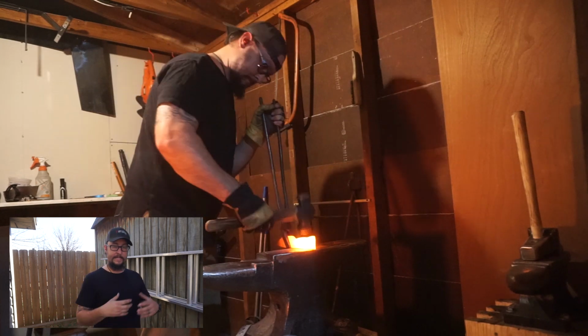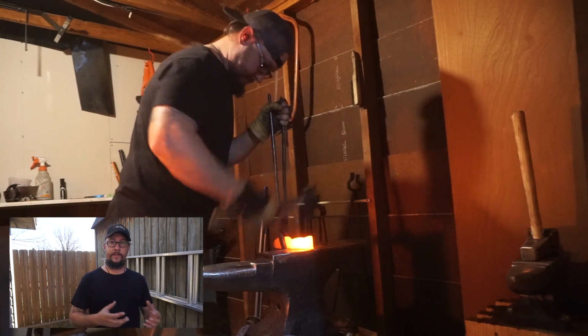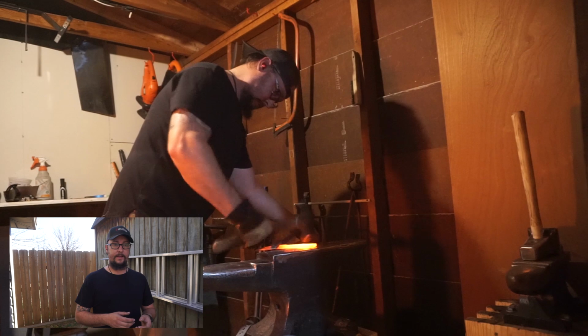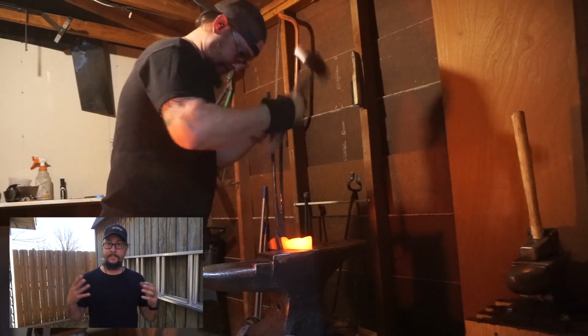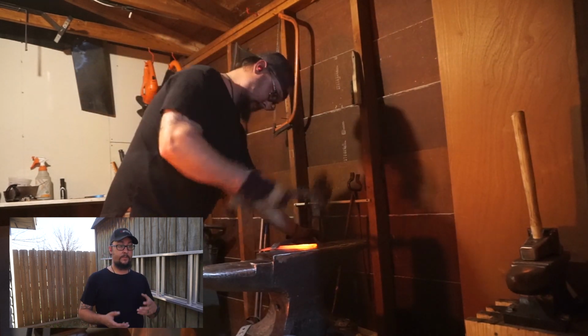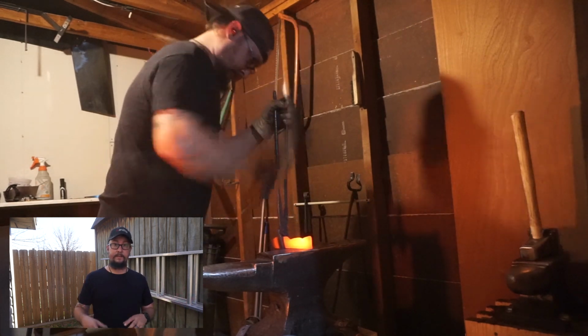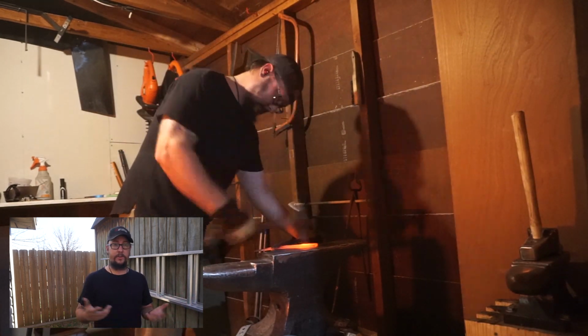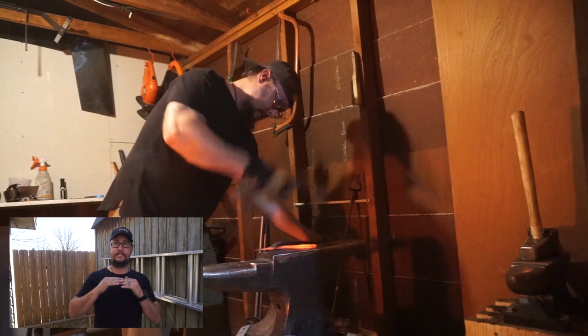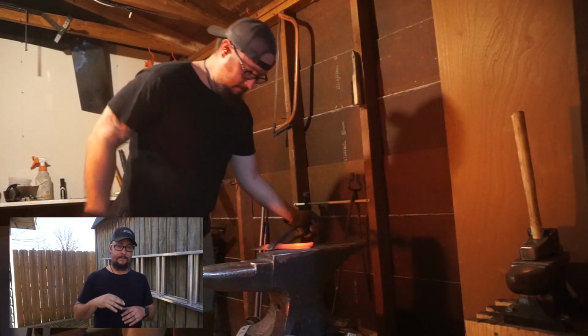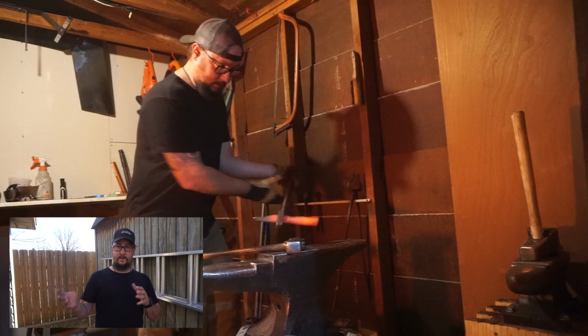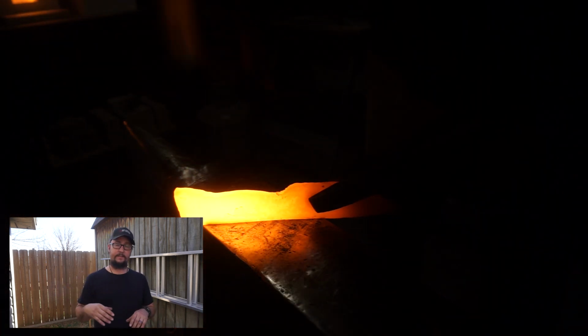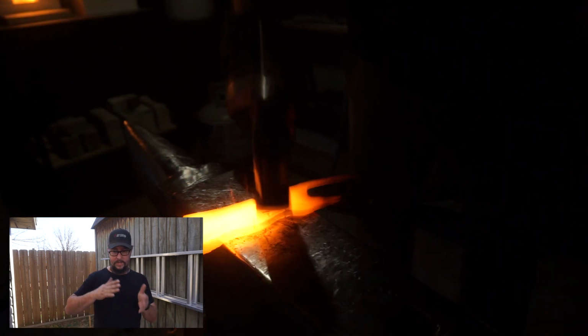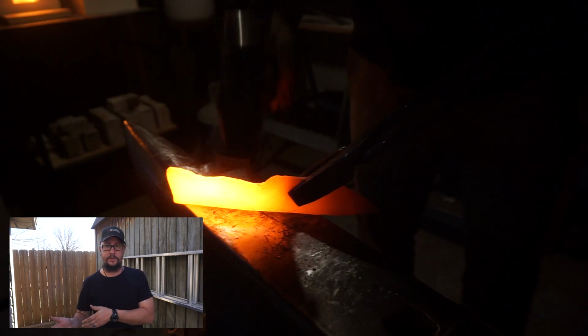So when it comes to heat treating, there's a lot of different ways to heat treat steel. A lot of steels have different types of heat treating. The easiest one, again, is going to be like that 1080, where all you've got to do is go to non-magnetic and then heat just past that. And for me, it's about an orangish color. Get that. Go ahead, quench it in 120 degree peanut oil.